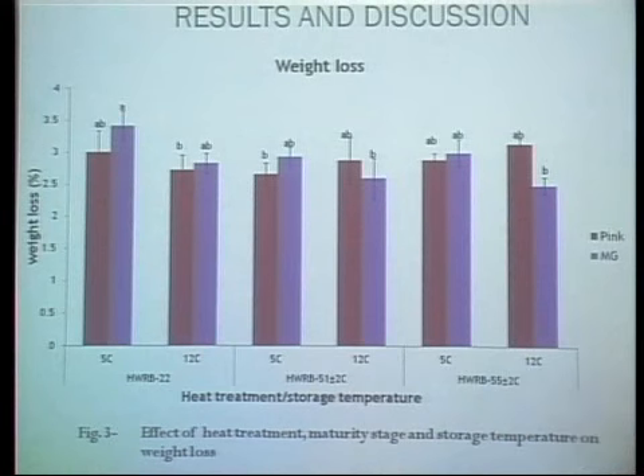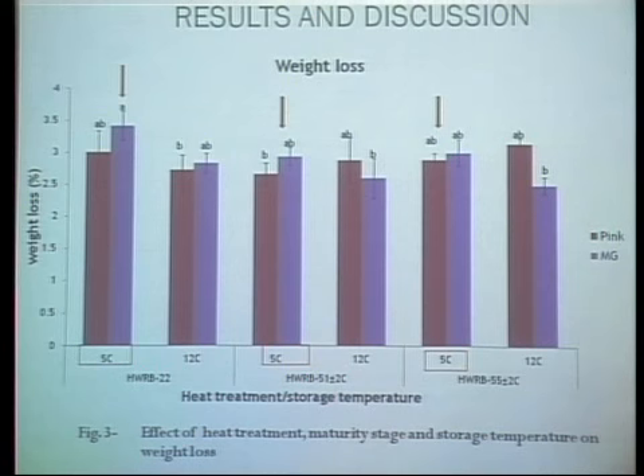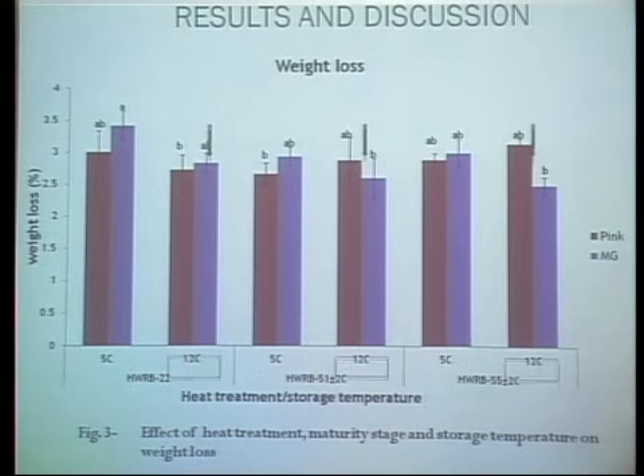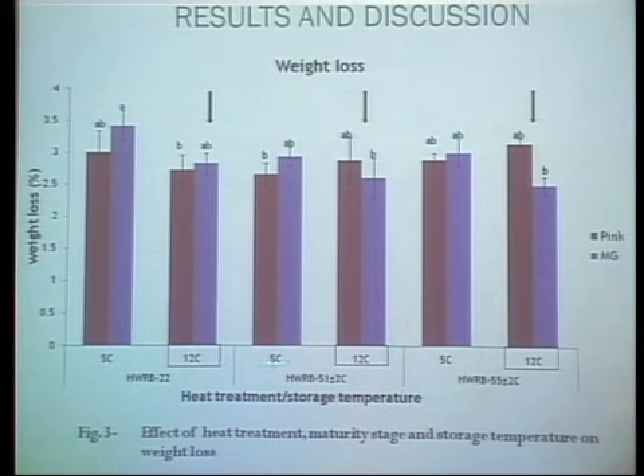All right. Now the next slide is the weight loss, and for the weight loss, we never had any interaction between the heat treatment, the maturity stage, and the storage temperature, but we noticed that there was interaction between the maturity stage and the temperature. And as you can see, at 5, when the fruit was stored at 5, you notice that the matured green lost weight, even though there was no significant difference. And then at 12, except in the control, we notice that the matured green lost weight more than the pink, whereas in the other one it is the other way around.